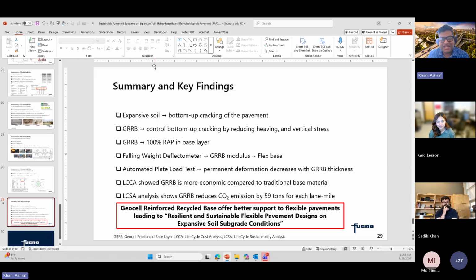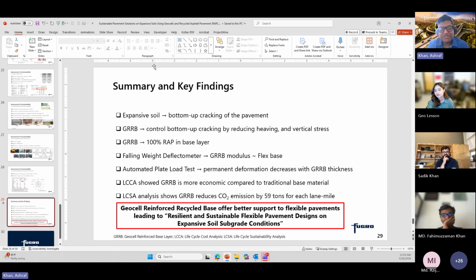Yes, obviously. The first challenge is you have to convince the agency. In this case, TxDOT was the agency that we had to prove, hey, we can use the geocell in the field, but we don't have enough data to prove it to them. So we need some data. We need to convince them to prepare the test sections. Another thing, you cannot construct a full unreinforced section on the main road because they're not going to allow their pavement to deteriorate. So the unreinforced section used for this study was limited to 1 foot by 15 feet, a very small section, which gave us some idea, but that was the main limitation. We cannot do a full unreinforced section to compare with the geocell to prove the performance.